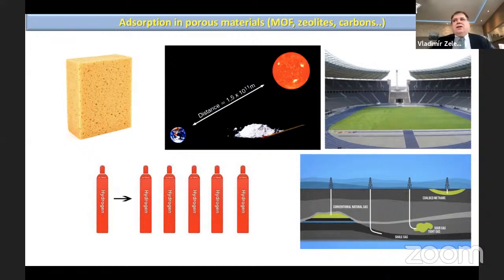For example, if we consider the pore system in some zeolite, 1 gram of zeolite can have channels, or these pores, with a length 4 times longer than the distance from Earth to the Sun. And 1 gram of metal organic framework can have a surface area 1 or 2 times larger than a soccer field. So this is the advantage of these materials, and the phenomenon of adsorption is special, is unique. And when you fill a pressure cylinder with metal organic framework, you can put inside this cylinder maybe 10 times more gas than in an empty pressurized cylinder, due to the phenomenon of adsorption. So this is the idea of the use of such materials.